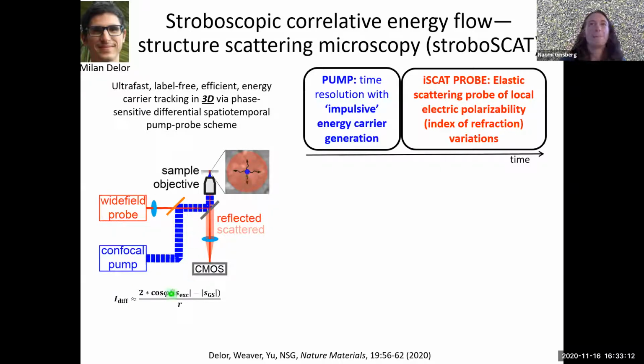So we're measuring basically a differential signal. It's the difference between the amount of scattering we see when the pump is on versus when the pump is off. And that's owing essentially to a variation in the optical polarizability that the quasi-particles induce. So we can watch the expansion of initially localized quasi-particle distributions, like shown in this blue spot here. And then I should just say this is really quick.